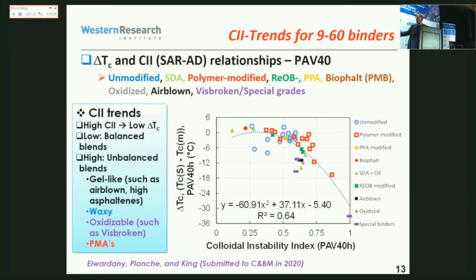Okay. So what we find out is that when we look at it, those are hard-grade asphalt. And in fact, we took that one because it's used in Europe to make high modulus mixes. Well, okay, it's not on the surface, so that should work if the climate is not too tough. But it's highly structured binders. So those are gel, sort of gel-like binders.